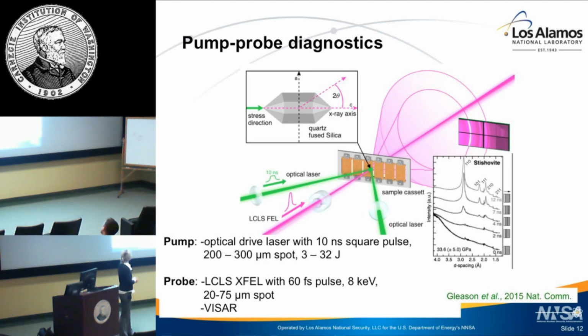On the lower right side here, I just show little snapshots of different time delays. So the shock is launched in our sample. That shock front travels at a certain velocity. I select when I probe with the X-rays to see volume fraction shocked and unshocked, right? And that is then resolved in the downstream diffraction.